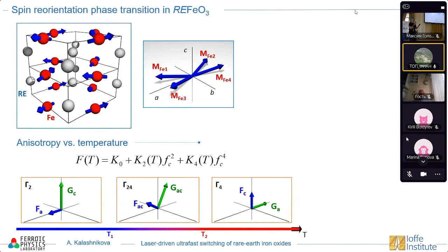And first, rare earth orthoferrites. They are quite well known in magnetism materials. These are dielectrics. Magnetization here comes from the ordering of iron magnetic moments. In principle, they form 4 antiferromagnetically coupled sublattices. There is also a small canting of the sublattices, so it's a weak ferromagnet. We can describe it using ferromagnetic and antiferromagnetic vectors, F and G.